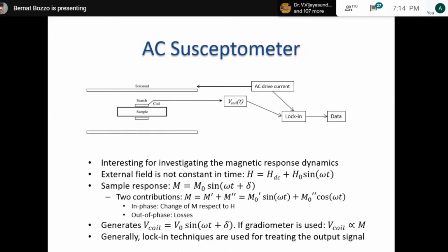In order to treat this delay, we need to separate the magnetic response into two contributions, M prime and M double prime. M prime is the response which is in phase with the applied magnetic field, and M double prime is the out-of-phase one, which is delayed by 90 degrees with respect to the applied magnetic field. These two contributions have two meanings. The in-phase one gives you the local change of magnetism with respect to the applied field, and the out-of-phase contribution is related to losses.